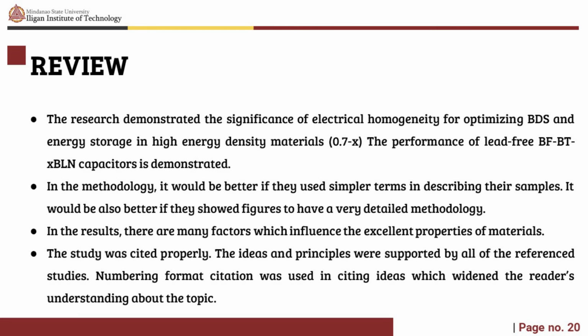The research demonstrated the significance of electrical homogeneity for optimizing BDS and energy storage in high energy density materials. The performance of lead-free BF-BT-xBLN capacitors is demonstrated. This yields a record recovered energy density, or WREC, of 13.8 joules per cubic centimeter and an efficiency of 81% for bulk ceramics and multilayers. Temperature stable up to 100 degrees Celsius, frequency independent between 10 and 10^2 Hz, and low strain characterize multilayers. These characteristics may be advantageous in pulsed power systems.